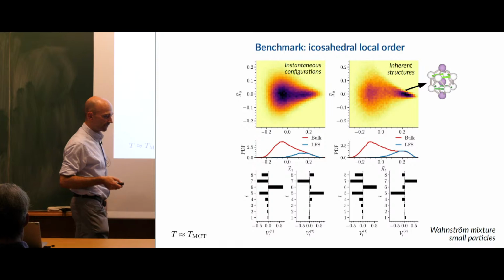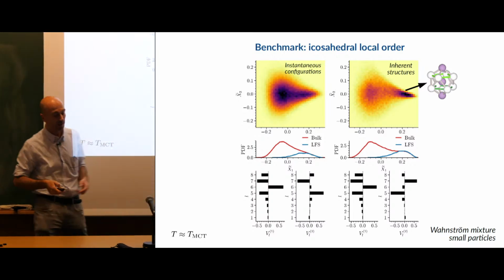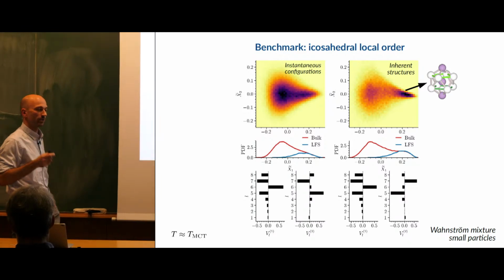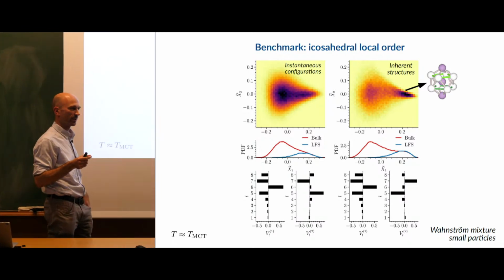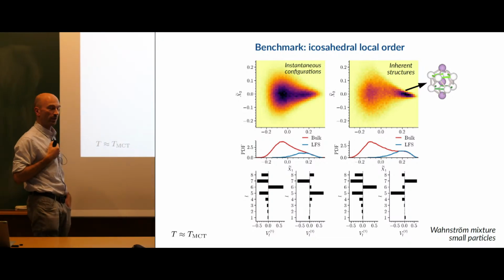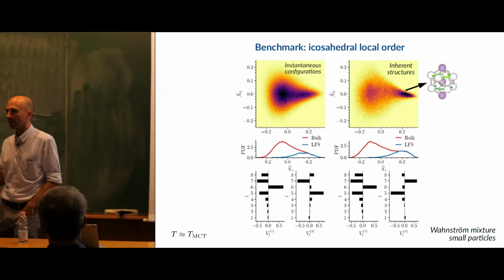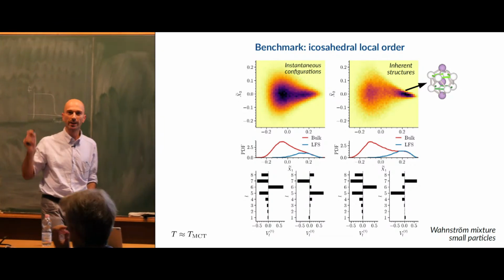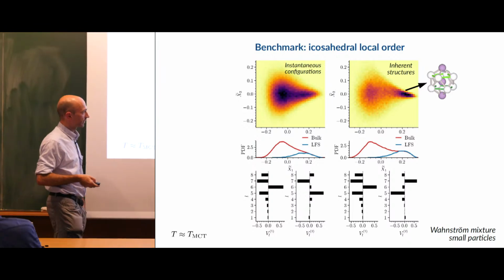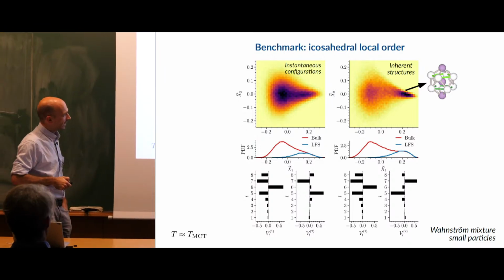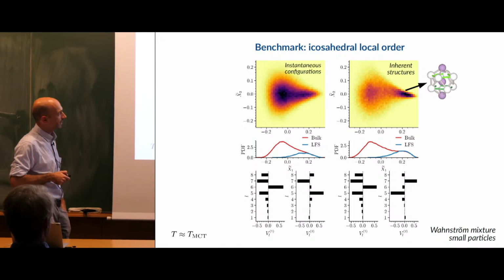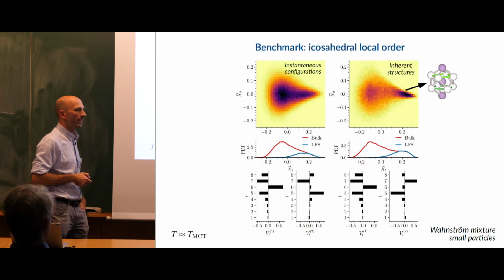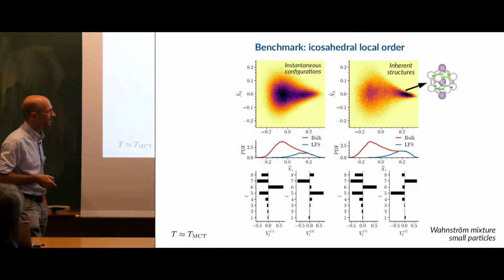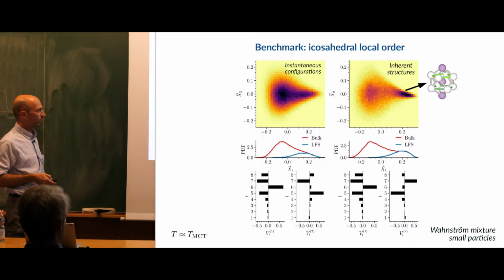And if you cross this information with a Voronoi-based LFS, you will recognize that the lobe is indeed due to the icosahedral structures that are the locally favored structure of this system. So the method here seems to capture what we expected. There's a well-defined locally favored structure which appears as a lobe in this low-dimensional distribution of your reduced variables. These are the first eigenvectors of the covariance matrix. As expected, this eigenvector has a strong signal on the 6th order invariant and opposite signals of the neighboring invariants. So it again explains a bit what we have found in terms of icosahedral local order.